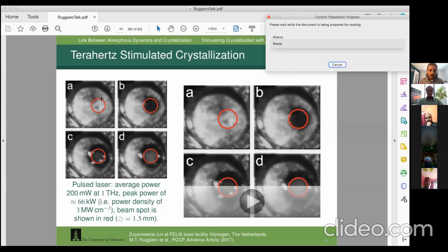But what it did induce, and what you see in these screenshots, is that the red circle is the beam diameter - it's actually a Gaussian beam, so it's the full width half max, which is why in some pictures the effect extends out a little bit. But this is the terahertz beam diameter exactly, as we measured when we made the figure.